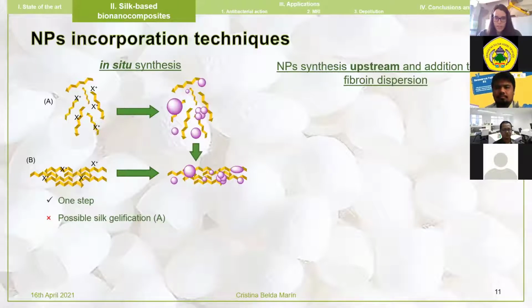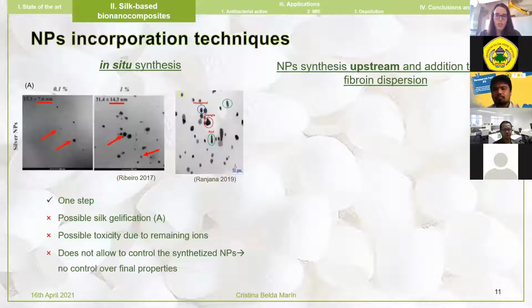However, silk solution is very delicate, and the incorporation of ions into the solution can induce gelification. Moreover, if metal ions remain in the material that we want to use for biomedical applications, for example, this could induce a toxic response. And finally, and much more important, as I told you before, properties of the nanoparticles are dependent on the size, shape, and surface chemistry. And this is not a parameter that we can control through this technique.